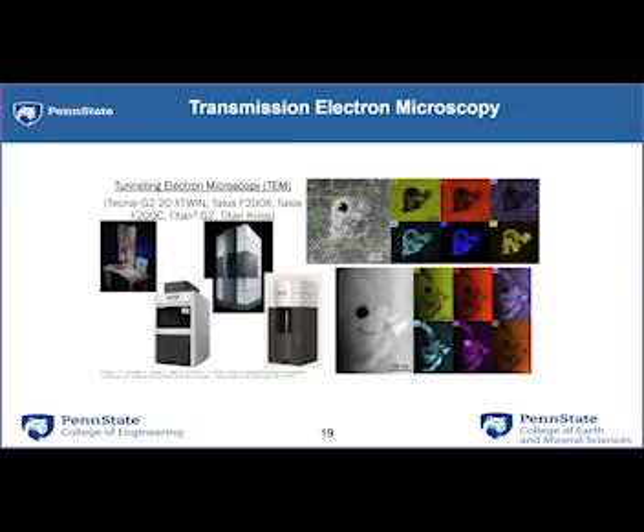And if you really want to get fancy, you can get into transmission electron microscopy, and we can look at, you know, atom layer type things. You start seeing that we're characterizing oxide inclusions. This is in a nickel-based alloy that is shown here. And what it allowed us to do in this image was to resolve dislocations across the material. These are small defects in the metallic systems, and understand how a precipitate grew off an oxide inclusion that existed. And this is from a powder part.